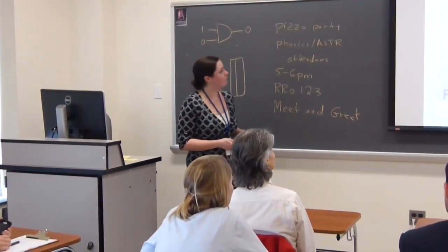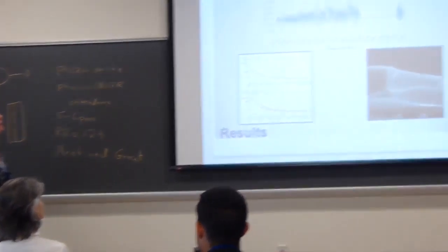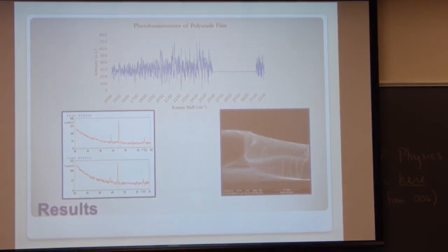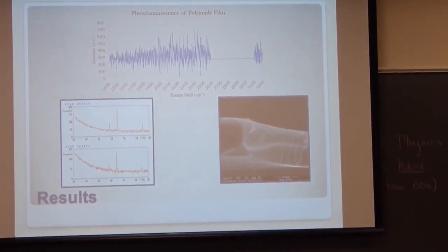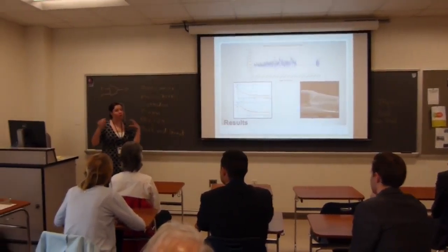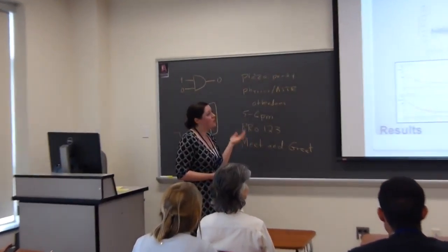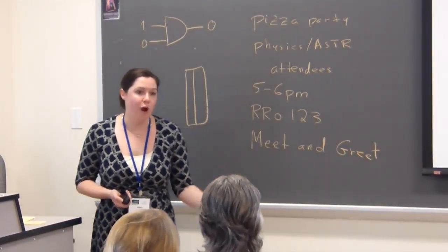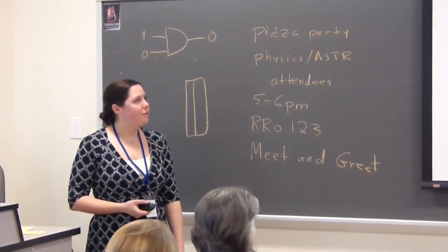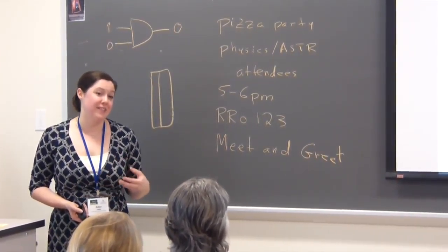Yeah? Do you, can you explain a little about the photoluminescence? So, a little bit, yes. Dr. Perkins is helping with this a lot. So, basically what it means is that there's too much noise in there. And that I've actually tried reducing the power of the laser. I know that you had talked about that a little bit in yours. That you wanted more information. We had too much information in ours. So, there's basically too many photons scattering around in there. And we overloaded the CCD right around 2700 wave numbers. Which is right where we were expecting for a graphene signature. So, it's sort of just a bad coincidence. But, we were able, there are ways to get around that. It's just that the equipment that we have here doesn't have that capability. Thank you.